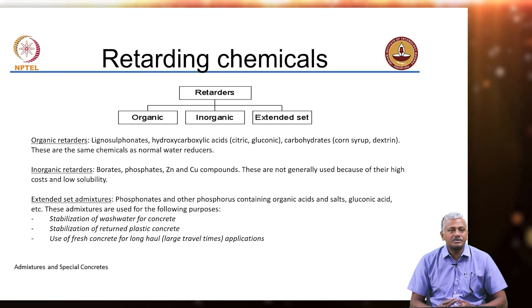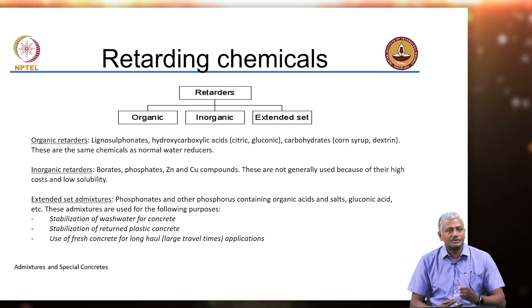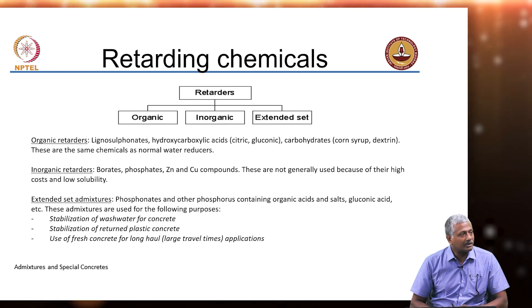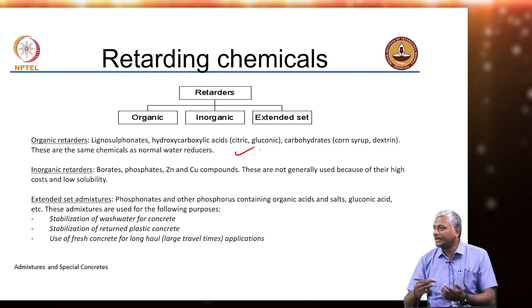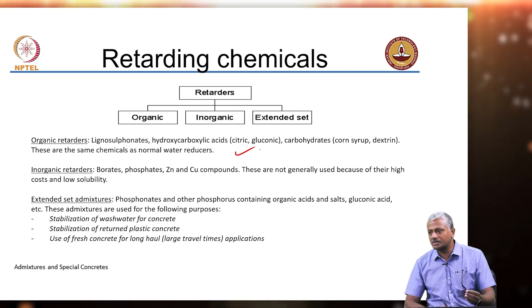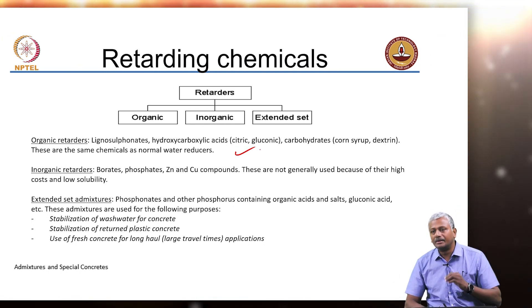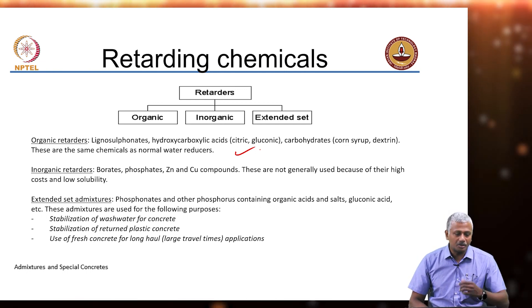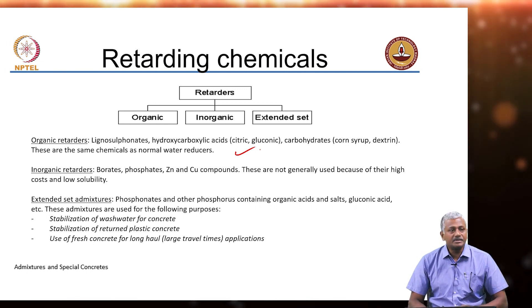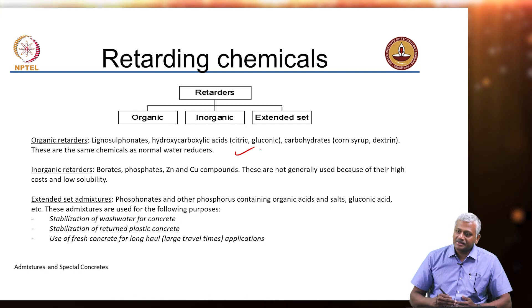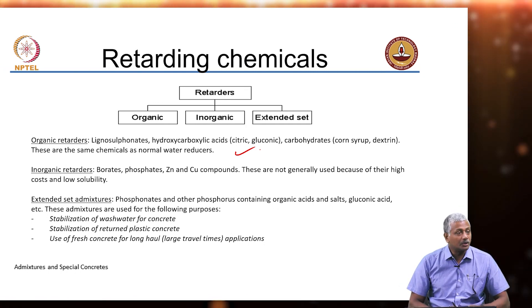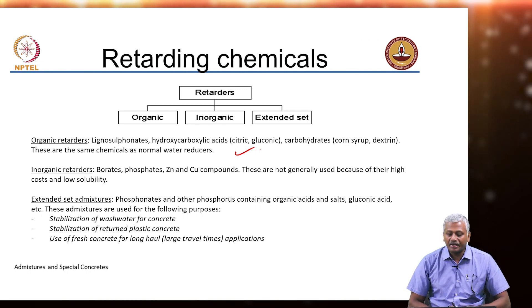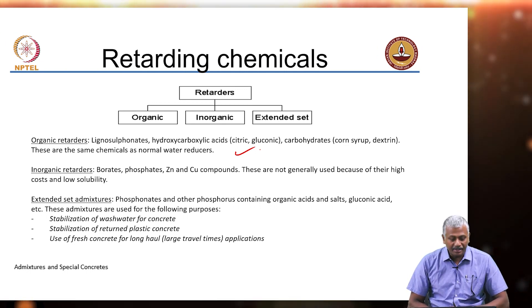The advantage here is that you get a dual effect — not just retardation but also slump retention or initial workability. In some instances you want to really extend the workability for a very long time. That is where you would use phosphonates and phosphorus-containing organic acids and salts, sometimes gluconic acid.